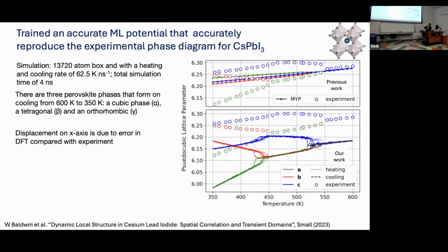In our calculations, these solid lines are all calculations compared to the experimental result that I just showed on the previous slide. So we took that from the publication, and you can see that our model gets qualitatively the correct phase diagram. It's shifted down. So here, the bottom lattice vector is about 6 angstroms as opposed to 6.15 angstroms.